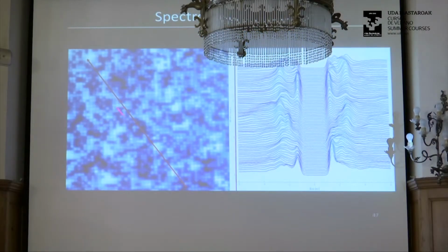Okay, now if you were to take a line cut across this material and measure a spectrum at each point, here I'm showing you spectroscopy measured from this point to this point, right? And you can see here's a beautiful superconducting gap. The bottom here goes to 0. It's absolutely flat, and it goes to 0, okay? One interesting thing you see from this line cut is the gap varies quite a bit from position to position. The other interesting thing is there are multiple gaps. There's not just one gap.